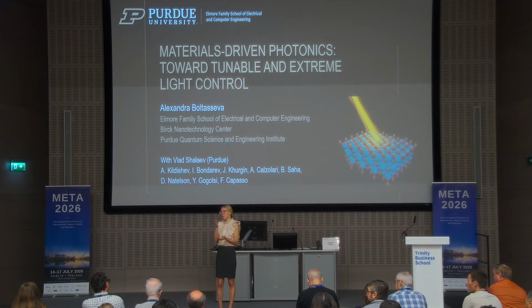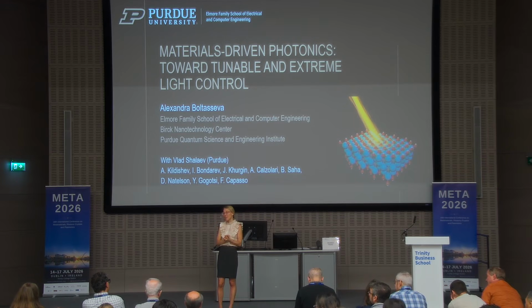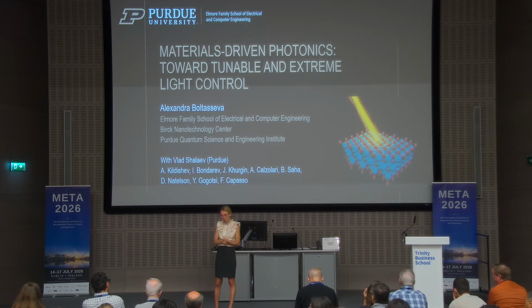So playing around with thickness just gives us a good starting point, because we want to hit this regime where we are sitting in the Wigner crystallization stage on the phase diagram. When you are there, you can do other things like gating, because sitting near this phase transition between the Wigner crystal and the point where it's melting would give us a lot of opportunity for active tuning. We just discussed it with Eli yesterday, that that's something very interesting to see. So we would love to explore that, and we will.